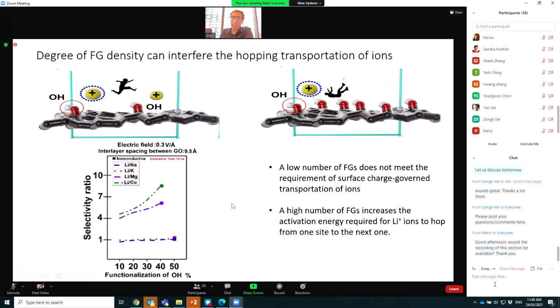The other very important factor is the functional group density or charge density. What we found is that when you have a low number of functional groups, it doesn't meet the requirements for surface charge governed transport. So you couldn't jump, for example, if the mechanism is based on hopping. And if you have too many functional groups on your surface, it increases the activation energy, so you couldn't hop from one site to the other. We found that having functional groups below 10% and above 50% makes our membrane non-conducting, and it's very important to have an optimum point for the charge density on the surface.